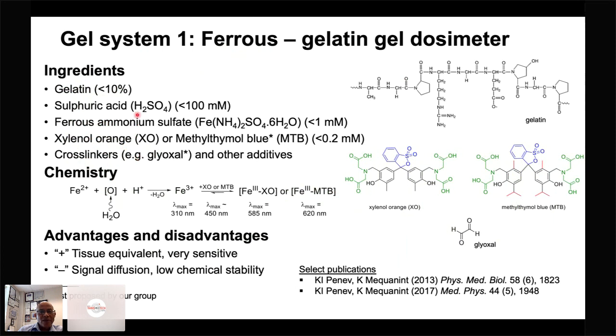And then we have used cross linkers. This field has been going for quite some time. Our contribution to this area is that we were the first one to propose to use glyoxal as a modifier for the gel. Now, initially we used it for a different purpose, but it turned out to be actually quite useful in terms of optimizing this particular hydrogel. Glyoxal, as you may know, is the smallest dialdehyde, and so we combine this gelatin with either xylenol orange, or we also used methyl thymol blue, which again is a ligand that we have used in our lab for the first time, and you can see the footnote in here.